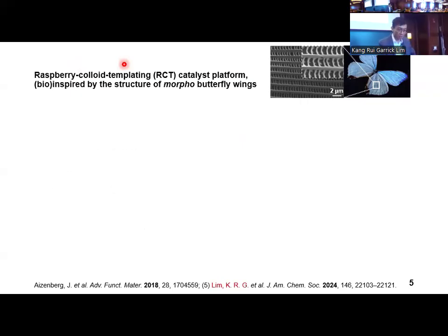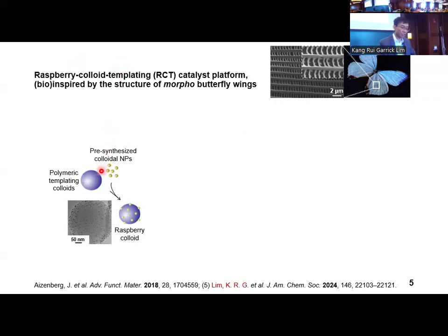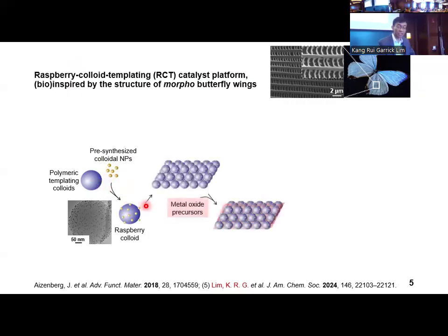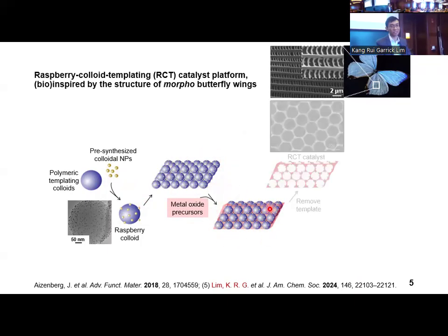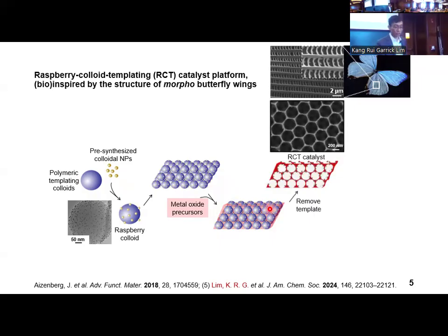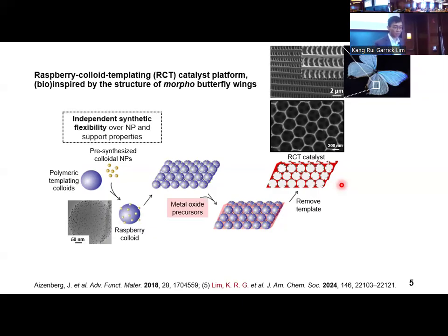In this RCT method, pre-synthesized colloidal nanoparticles are attached to templating colloids to form nanoparticle decorated raspberry colloids. These raspberry colloids are then self-assembled and filled with metal oxide precursors. A templating colloid removal step forms the support and yields the final RCT catalyst. The RCT method here seeks to address the two major limitations of the impregnation method.